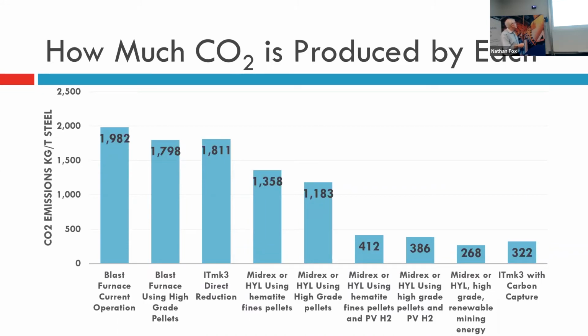If you produce hydrogen using electrolysis of water and solar cells to power that electrolysis, then you can reduce it to quite low figures. And these three figures here are showing what could be done. They're the sort of minimum areas of CO2 emissions that you could have if you used electrolytically produced hydrogen to reduce iron oxide. And if you're able to capture the CO2 from ITmk3, or use charcoal in the ITmk3 process, so a biofuel, then you could produce iron using the ITmk3 process.